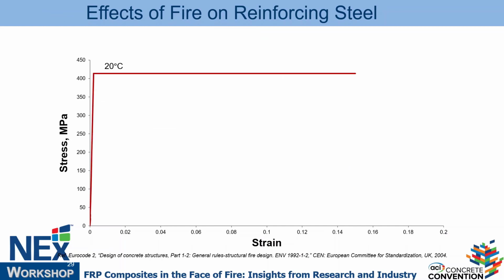Now let's look at the steel bar, similar. And I know it's a little bit aggressive, but assume a linear stress-strain diagram, and after that I have a plateau, and then there's a hardening that I'm not showing in there. This is the yielding, what we define as yielding, at ambient temperature close to 20 C, right? And then it goes to 400 degrees. I start losing stiffness. Strength doesn't degrade a lot, but then strength and stiffness both start dropping as I reach 500 C. The general rule is around 500 C plus minus, or 1,000 degrees Fahrenheit, 1100 in some cases, some people say, you lose close to 50% of the capacity of the steel.